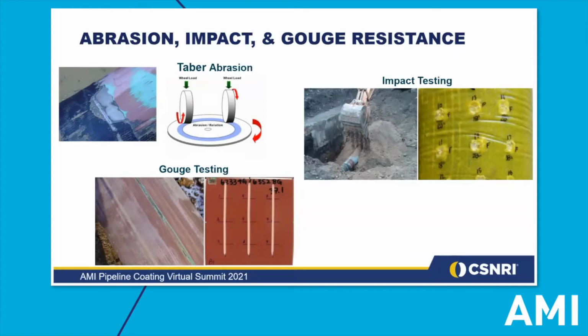Backfilling commonly puts a coating at risk on trenched pipelines. However, during a directional drill, standard abrasion or gouging can easily turn into impact when that raised weld profile, or larger rocks or debris remaining in the borehole, come into play. Rocks, particularly cobble, are known to break loose inside a borehole and can impact the coating. If impact resistance is a concern, using a fiber-reinforced composite will provide significantly greater impact protection. The key point to consider is that while coatings are designed to withstand some of the mechanical damage they may see, using a sacrificial mechanical protection will always improve the results and preserve the design life of the coating.